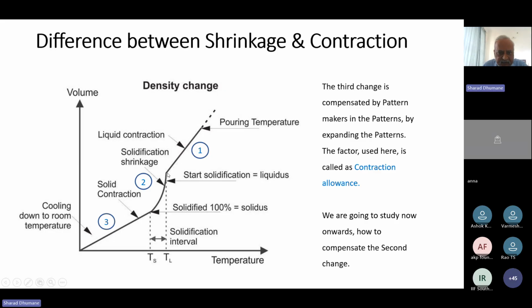So here it starts solidifying. Okay. And since our ductile iron solidifies in a freezing range, in a mushy zone, solidification occurs in a temperature range. There is no single temperature at which it solidifies. It solidifies over a temperature range or a solidification interval. So at this point it starts solidifying. This is your liquidus temperature. And at this point it solidifies completely. This is your solidus temperature. Between these two temperatures, it solidifies. Here at this point, it is 100% solidified. From here to here, it was liquid. From here to here, it is semi-liquid or semi-solid. And from here onwards, it is completely solid. Okay.